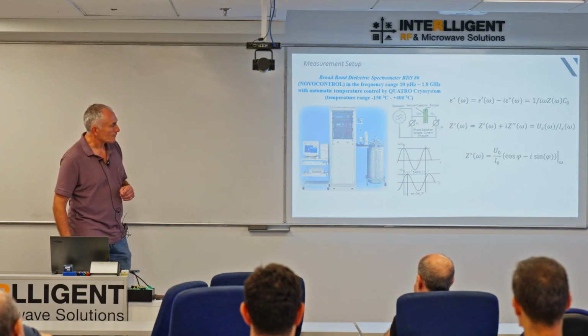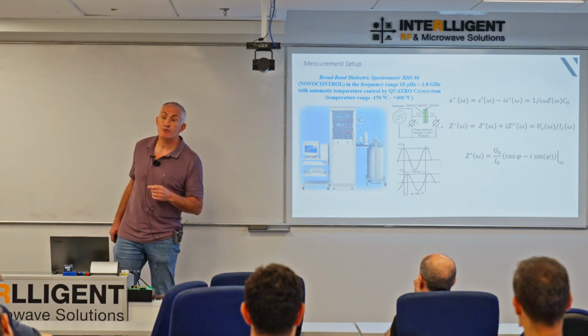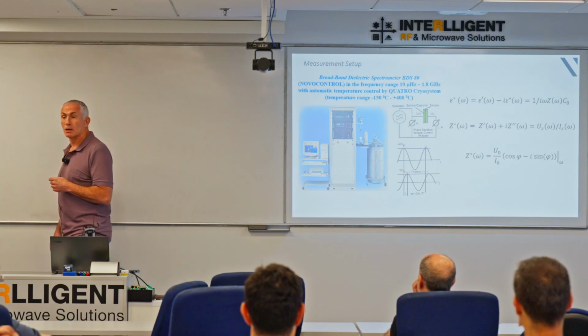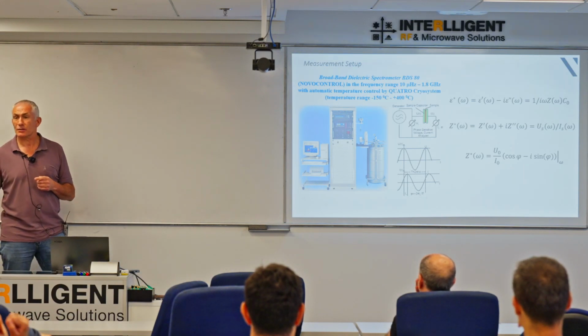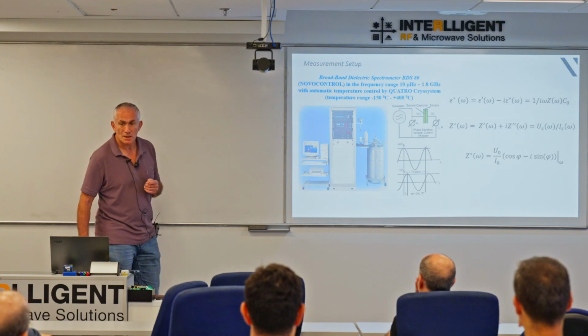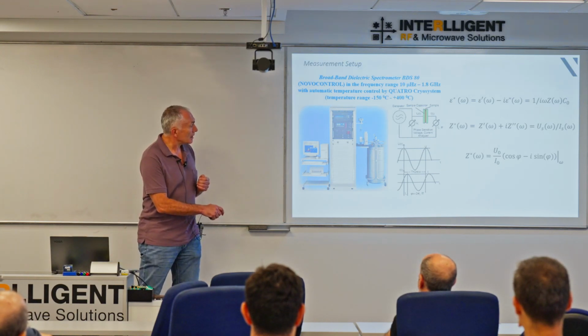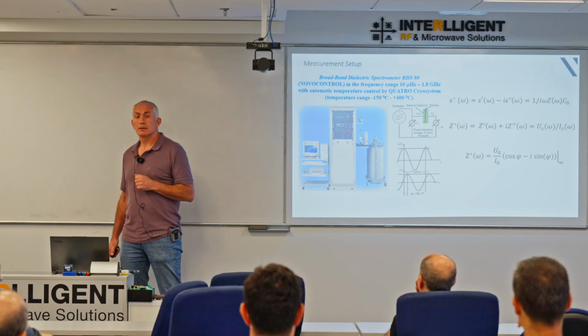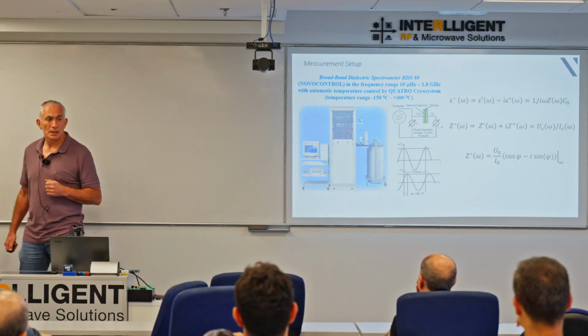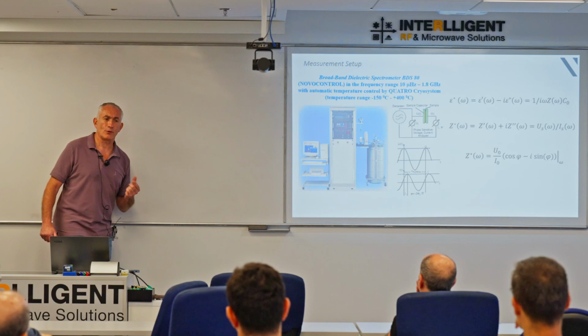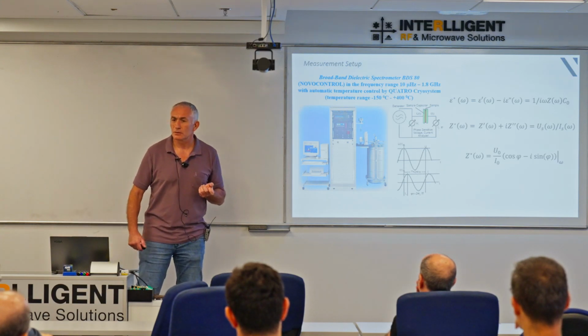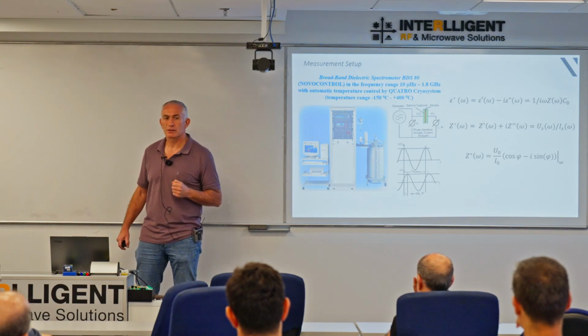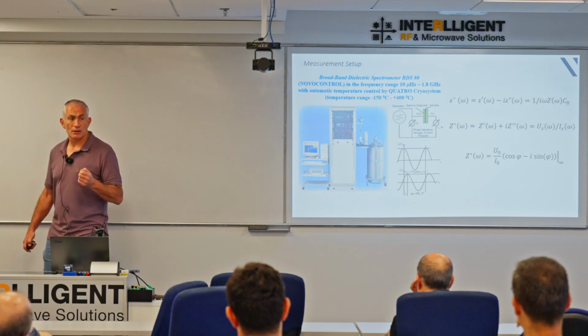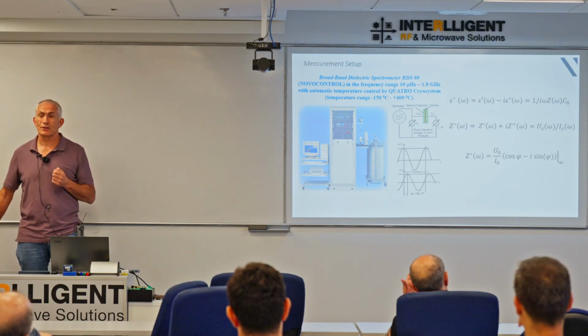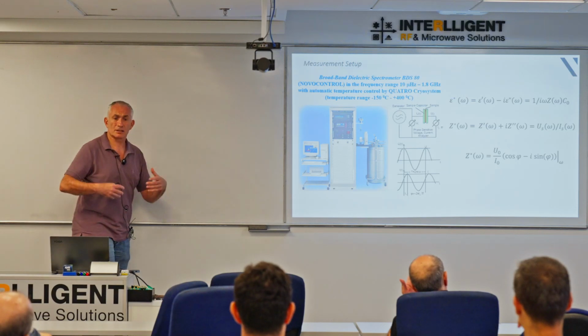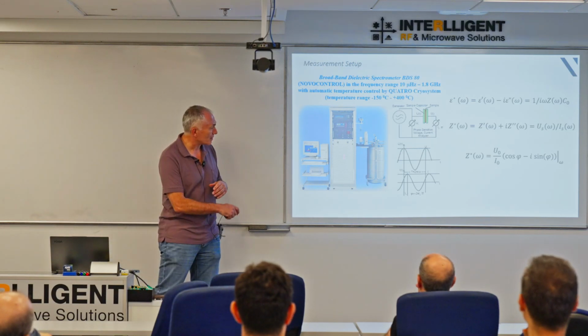Massive temperature range. And nowadays you can get this with special pressure units as well. So you can now measure your samples under gigapascal pressures and see what that does to them. You can get it with high electric field that you can apply. So you can apply over samples which may be only a millimeter thick, a 400 volt field. You can really stress your materials. And if you really want, you can then look at a four electrode system for this as well, and then you can start doing some electrochemistry with it too. So it's a very versatile machine.